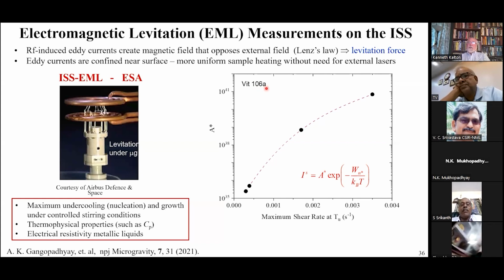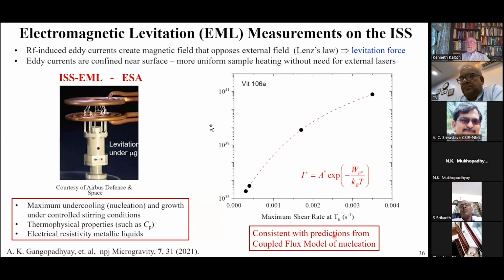This is Vitreloy 106A, which is a liquid that forms a bulk metallic glass. To crystallize it requires long-range diffusion. So we see, as I predicted, if we have very low stirring, then diffusion is going to be dominant during the nucleation step, and so you'll have a low nucleation rate and a lower value of A star. If you increase the stirring rate, then you bypass the need for diffusion. You're actually stirring the system, so you're bringing atoms to the cluster that way, and you end up seeing an increase in the nucleation rate. And this is consistent with the coupled flux model.